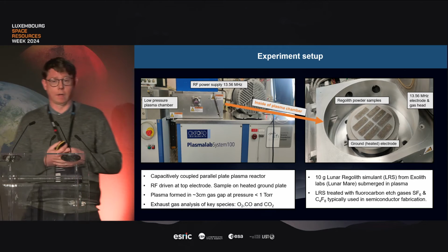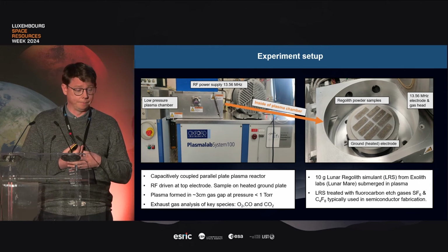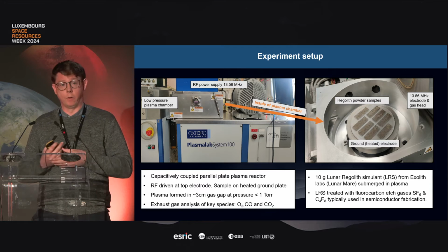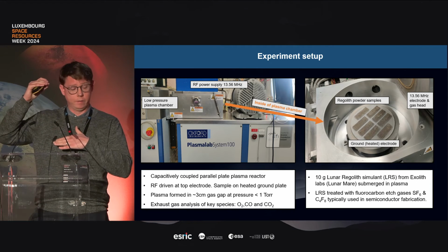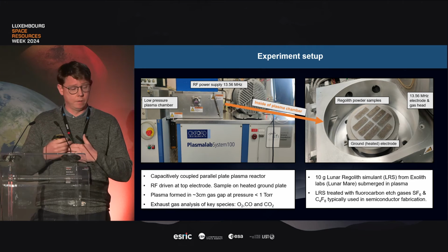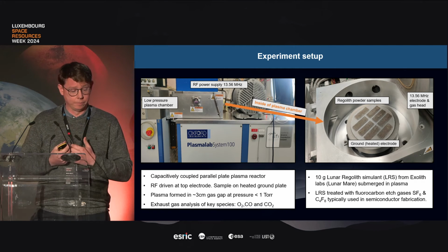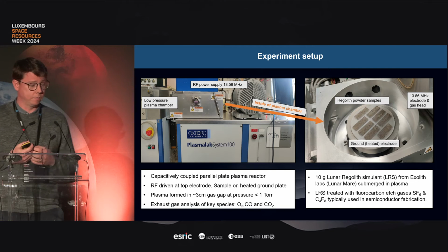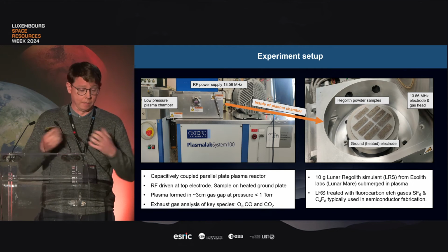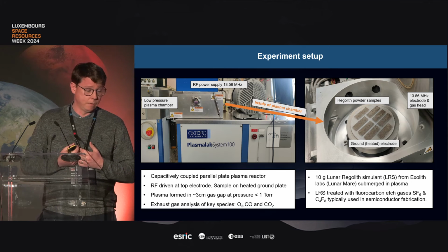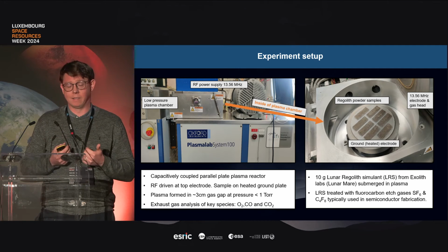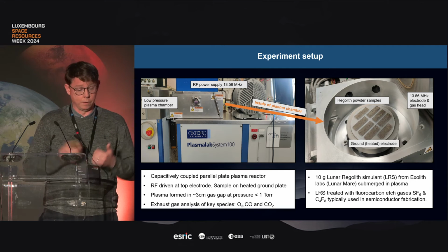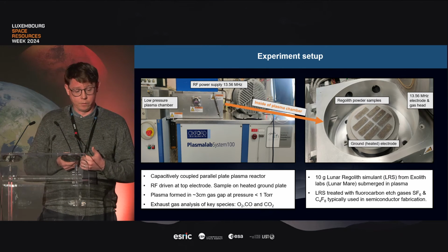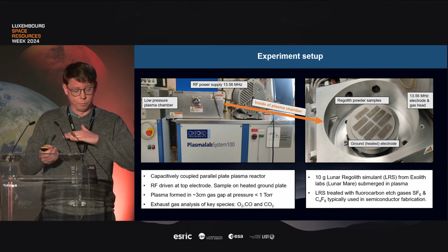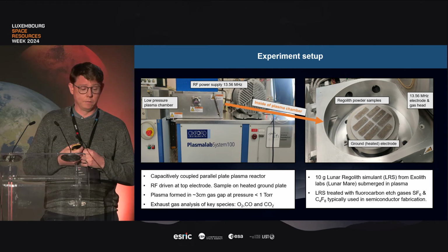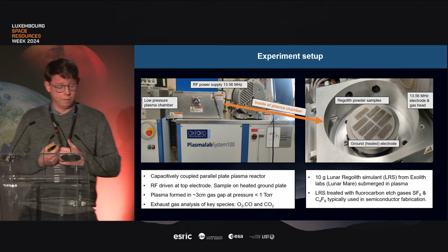So here's our setup. It's a capacitively coupled parallel plate plasma reactor from Oxford Instruments. It has two electrodes, a top electrode which is powered, and a bottom electrode separated at about 3 centimeters, which has a heated grounded electrode. It's driven at about 13 megahertz. The plasma is formed inside the gap at pressures of typically less than 1 torr. We are focusing for this study just on the gas analysis of oxygen, carbon monoxide, and carbon dioxide. So on the right-hand side here, you can see inside the reactor chamber with the lid pulled up. And we can see the regolith is placed, loose regolith is placed about 10 grams on the heated grounded electrode.